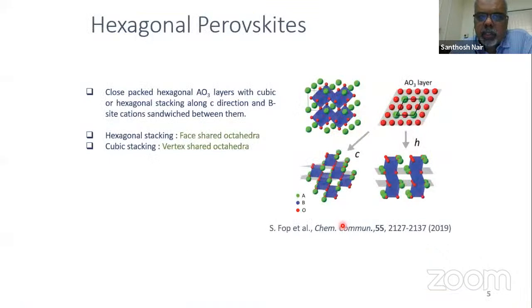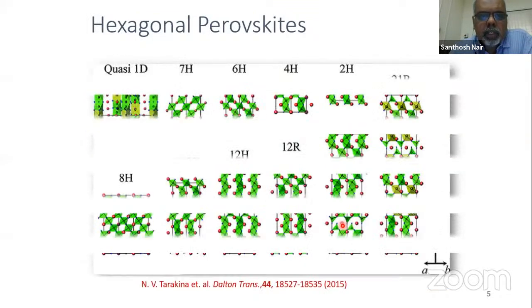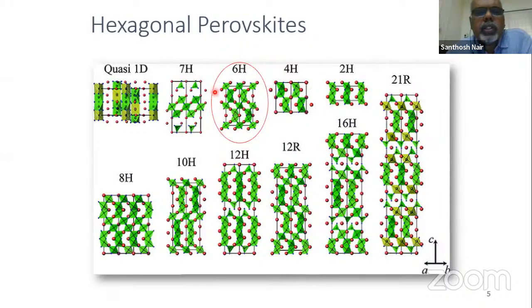The other structure I talked about is a hexagonal structure. I will not go much into this, but I just marked one called 6H perovskite. You can see this dimer, which is two face-sharing octahedra, connected to the next layer through corner-shared octahedra. In the face-sharing octahedra you have almost a direct metal-to-metal interaction, so that makes the magnetic interaction more interesting. There is a lot of interest in this 6H perovskite recently because of the observation of quantum spin liquid behavior and novel quantum phenomena, because of its triangular lattice formation. I will not go into that part of it.